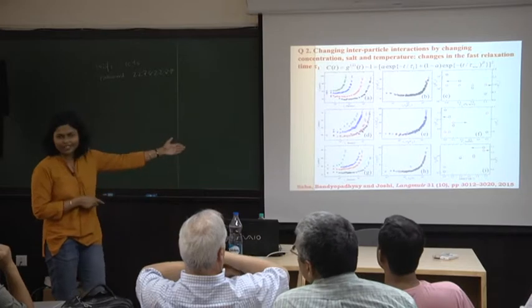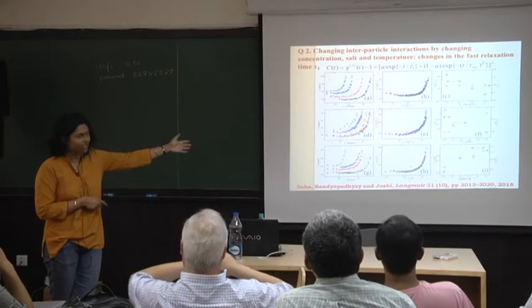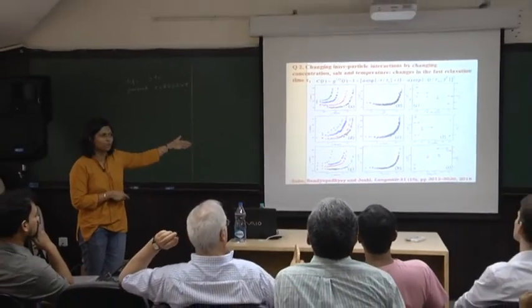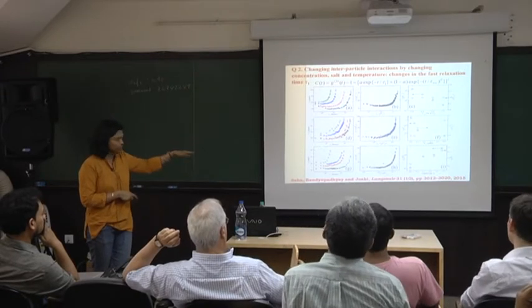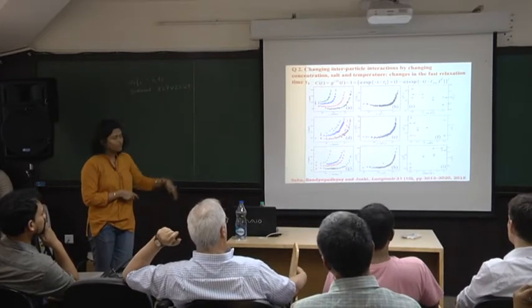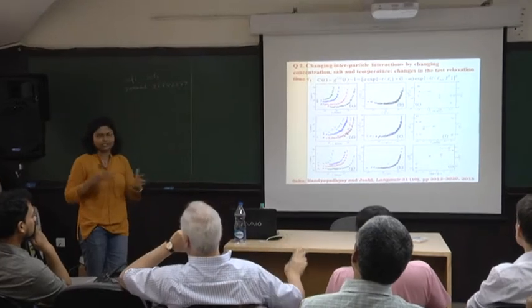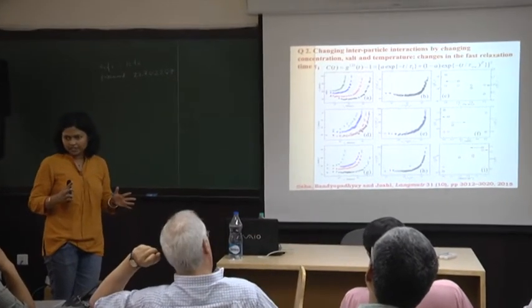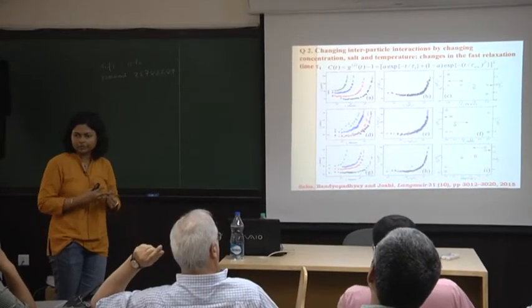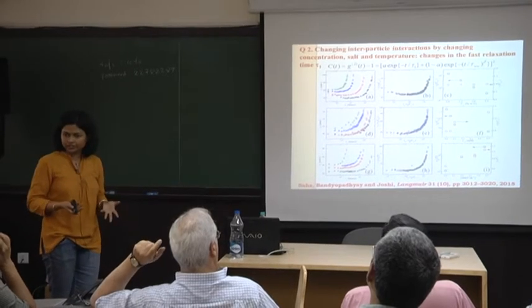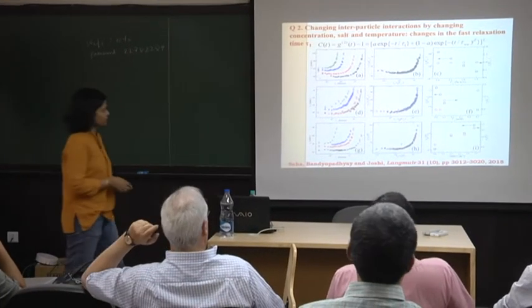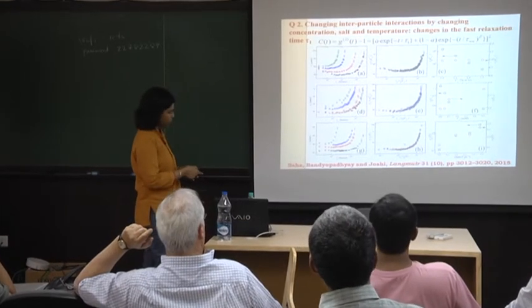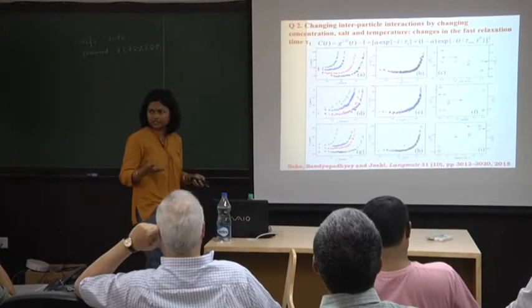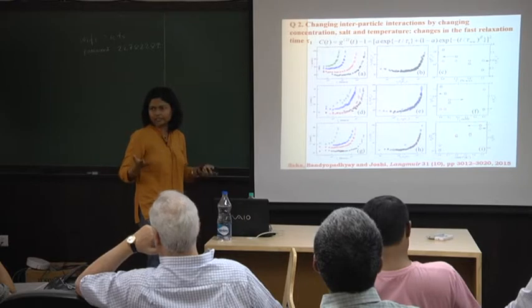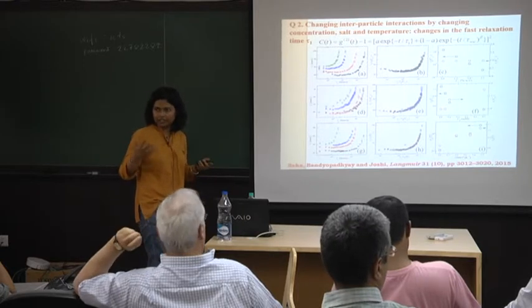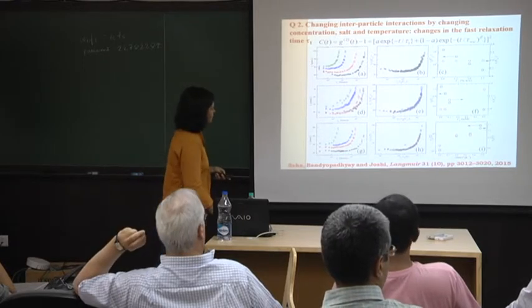This is our relaxation process. This is our fast relaxation time. You don't see it for the slow relaxation time, which I'll come to later. See, in this case, when you add salt, things happen very fast, right? You're screening the interaction, things happen very fast. You don't really notice that relaxation process very well. Okay? And here it's much more prominent for the low concentration because the dynamics in the low concentration clay is a lot slower than the other samples that we have here.